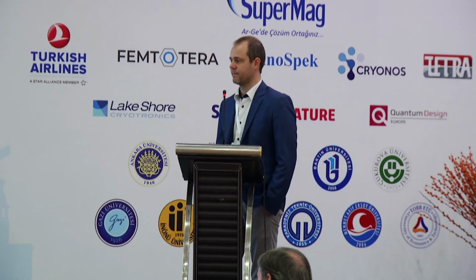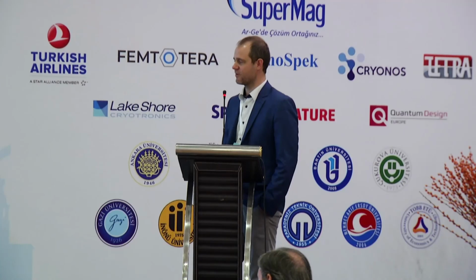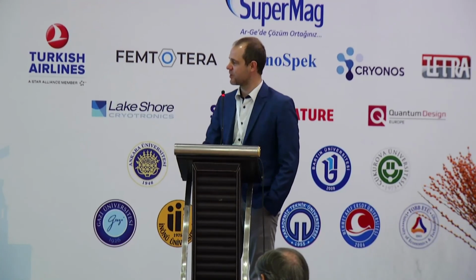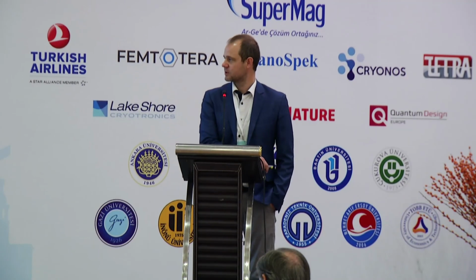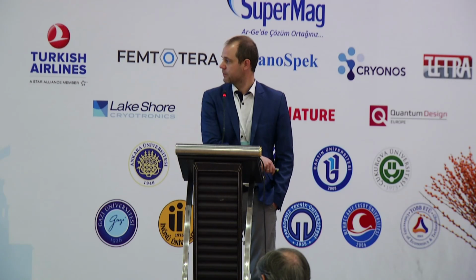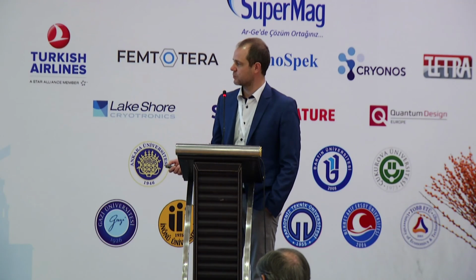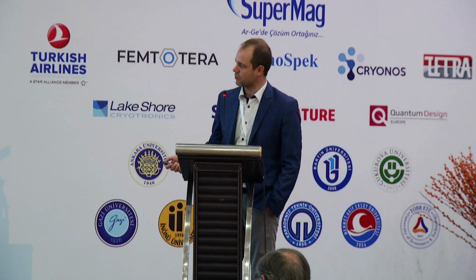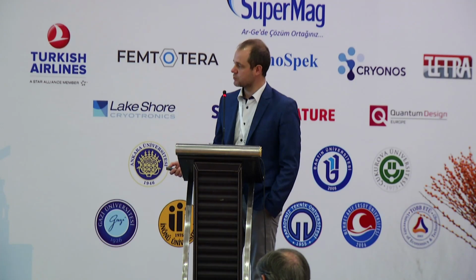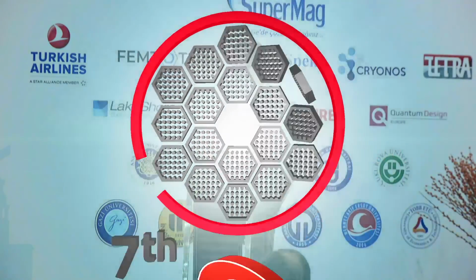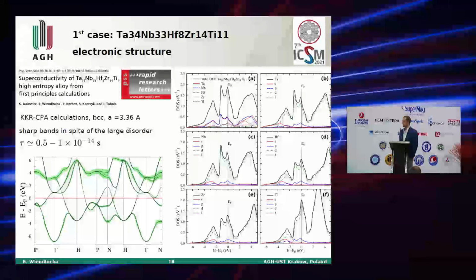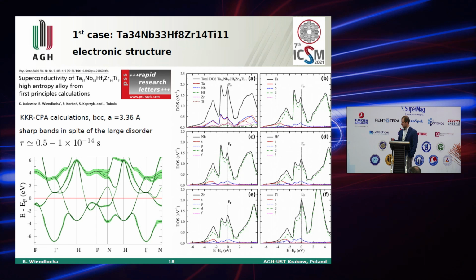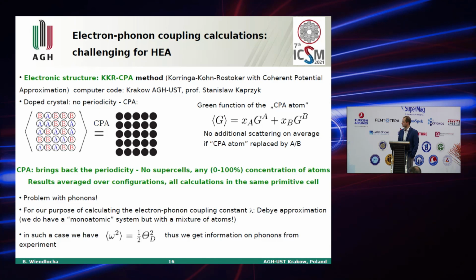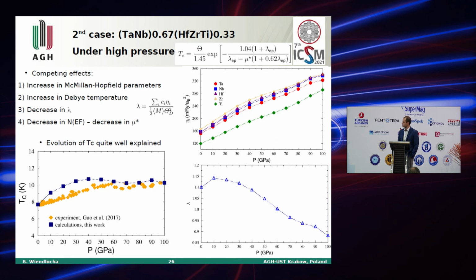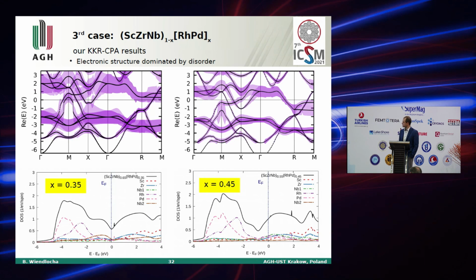And you said that there is no disorder. I'm a little bit surprised. No, there is no effect of disorder on dispersion relations. Yes, there is of course a disorder. But as I mentioned, you can see here those bands are very sharp, so they are not smeared. Those, for example, are smeared more than those on the Fermi surface. So there is no strong effect of disorder on electron dispersion relations. So the scattering time is like 10 to the minus 14, a typical value, I would say. This is not the case for the second material, which has strongly smeared bands. Yes, the effect of disorder is much more important in this case. So these bands are very, very strongly smeared. So this is due to disorder here.